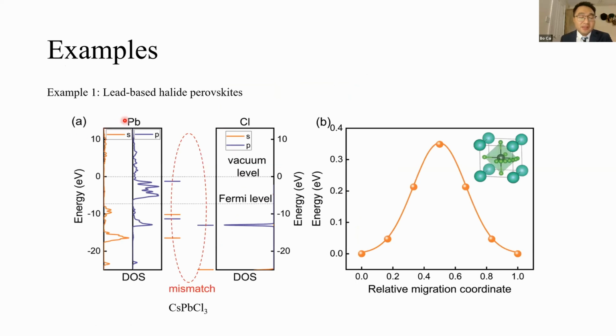Then we give four detailed examples. The first example: we check the band centers of CsPbCl3. We found that there is a big mismatch between the s orbitals of lead and the p orbitals of chlorine, using DFT simulations. Then we check the barriers. The barrier is extracted by the CI-NEB method.